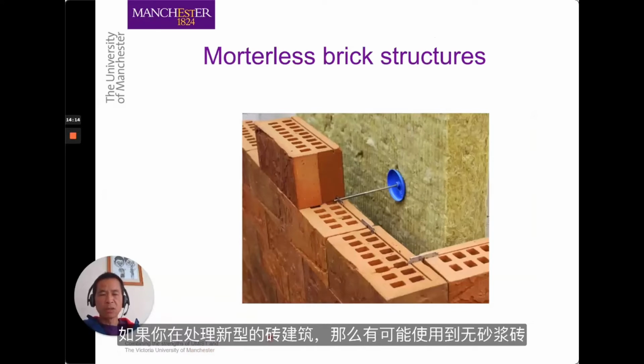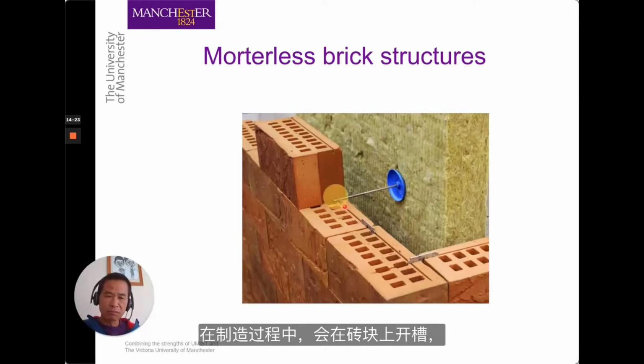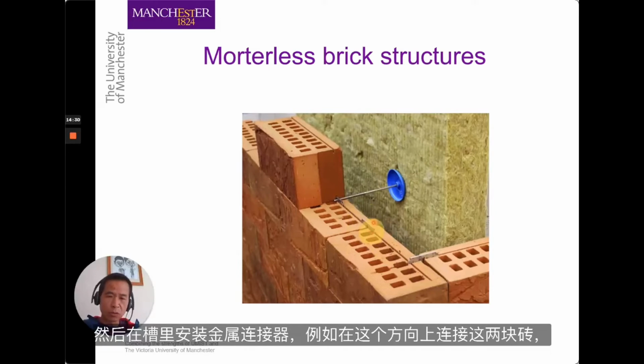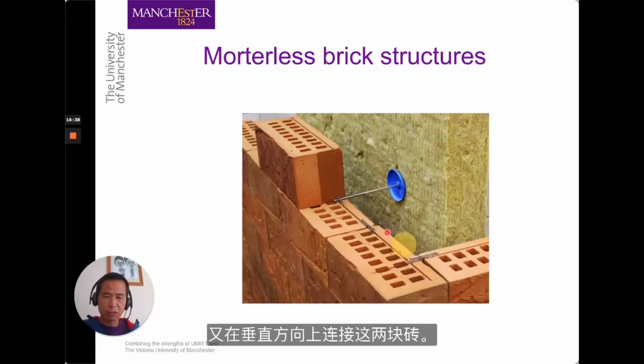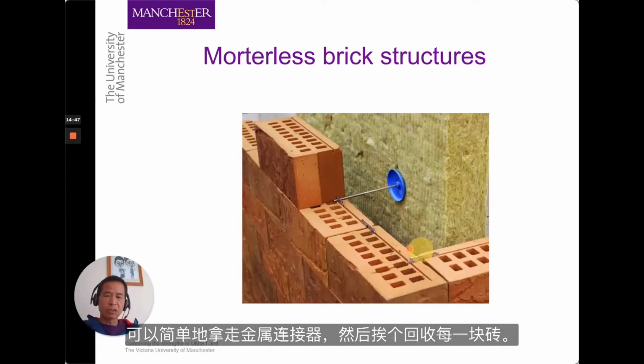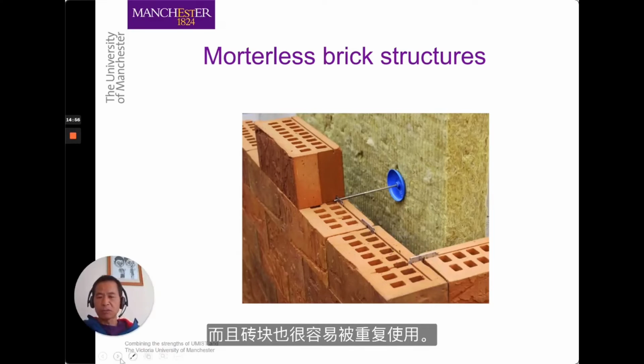If you're dealing with new brick construction, it might be possible to use so-called mortarless bricks. Here you make slots in the bricks during the manufacturing process, and then you install these metal connectors in the slots to link this brick to this brick in this direction, and to link this brick and that brick in the perpendicular direction. So at the end of the life of this brick construction, you can simply take away the metal connectors and then reclaim each brick one by one. And then bricks are bricks, they can be easily reused.